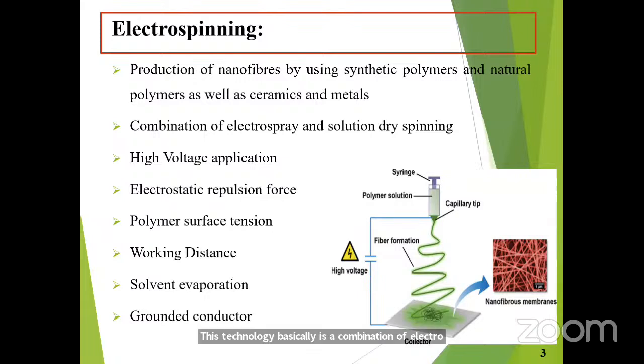In the electrospinning process, high voltage is applied between the needle tip of the polymer-containing syringe and the collector, which induces charge in the polymer solution. Induced charge in the polymer solution enables the deformation of the spherical droplet shape of the polymer to a conical shape. Furthermore, when the electrostatic repulsion force exceeds the polymer surface tension, a charged fine polymer jet ejects from the Taylor cone and is collected on the opposite pole of the electric field.